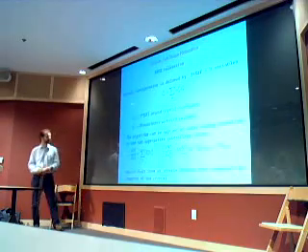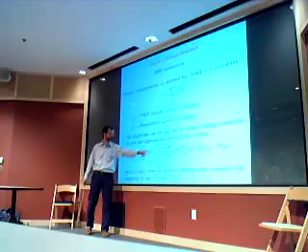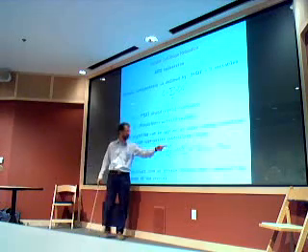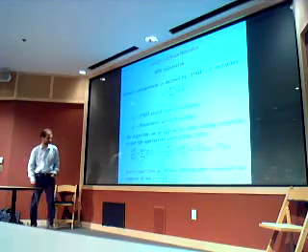The derivative of the enthalpy with respect to the internal coordinates in crystal coordinates is some linear combination of the forces multiplied by the Bravais lattice vectors, and the derivative of the enthalpy with respect to the Bravais lattice vectors is something related to the stress minus the external pressure that you are imposing, times the inverse of the lattice vectors matrix and the volume, and so on.